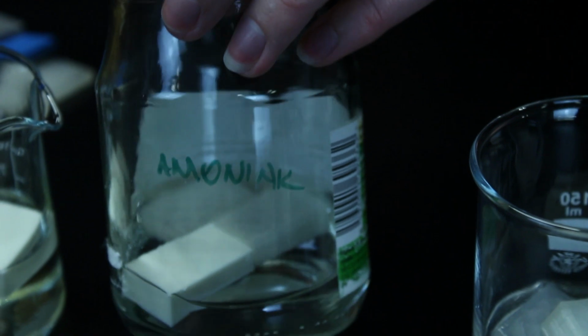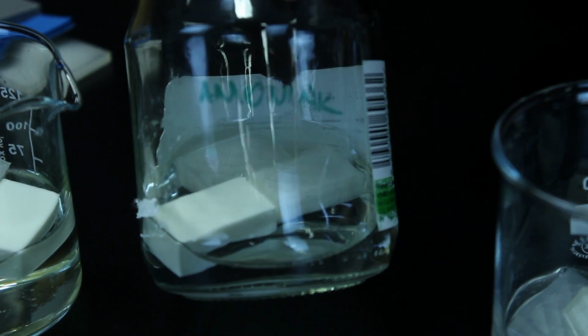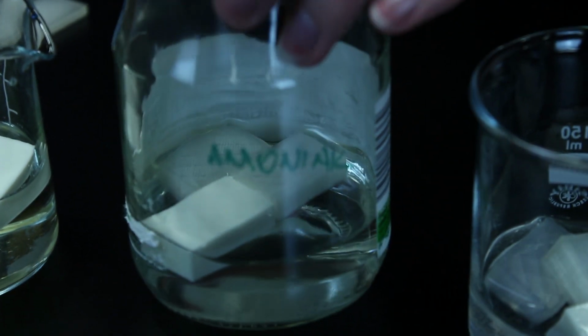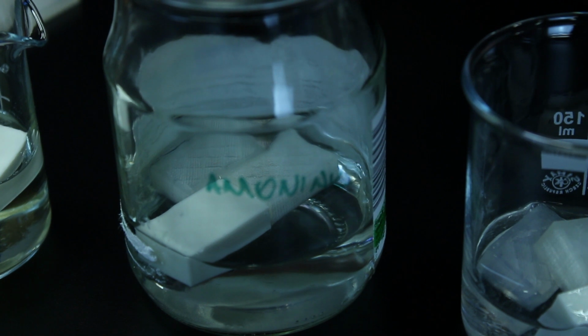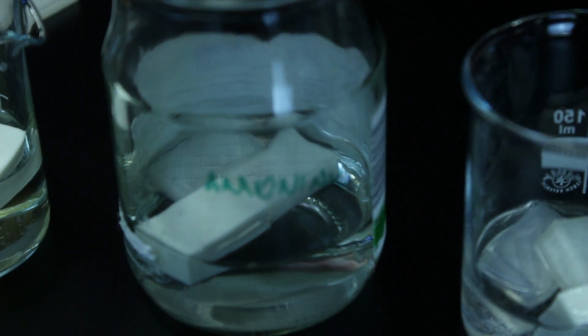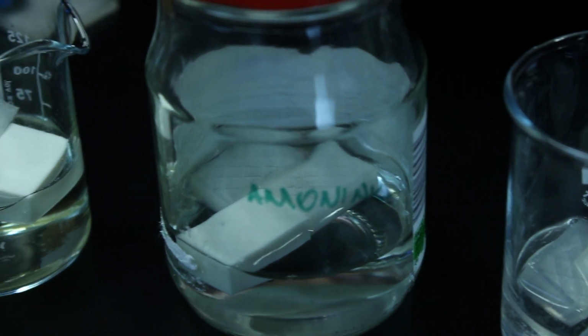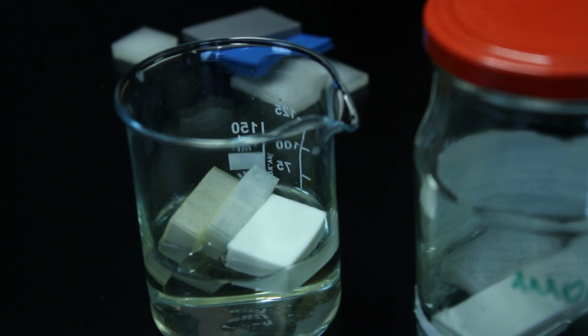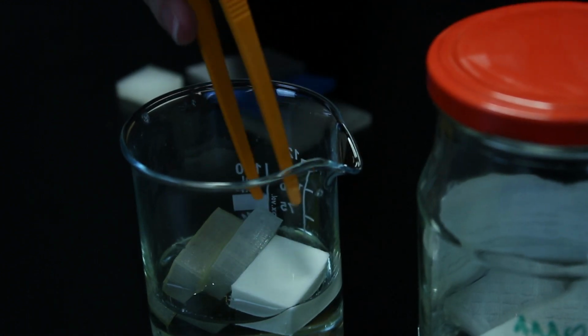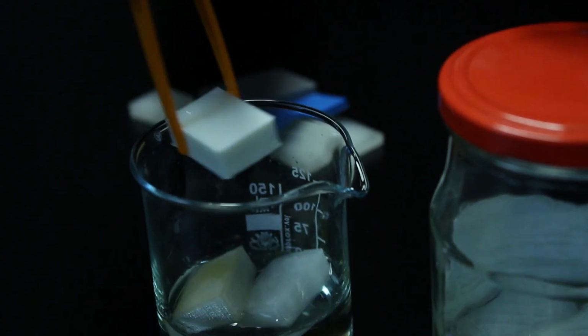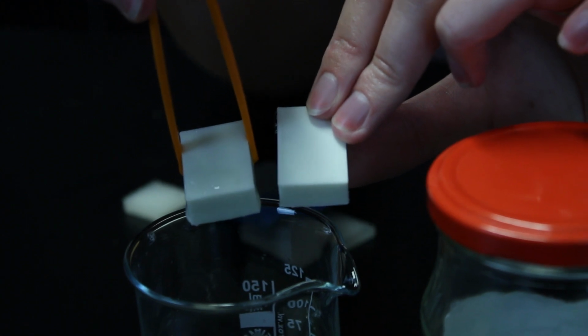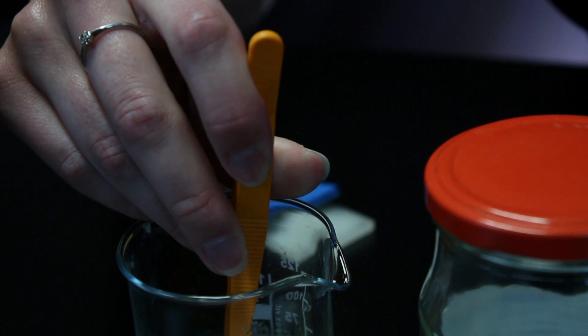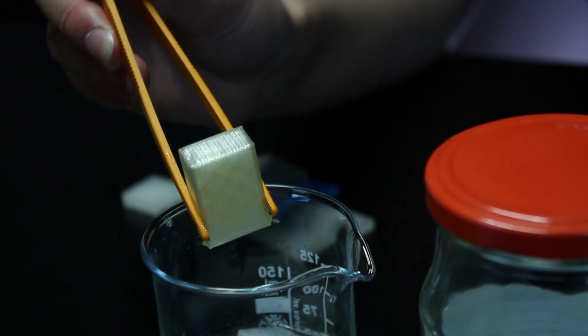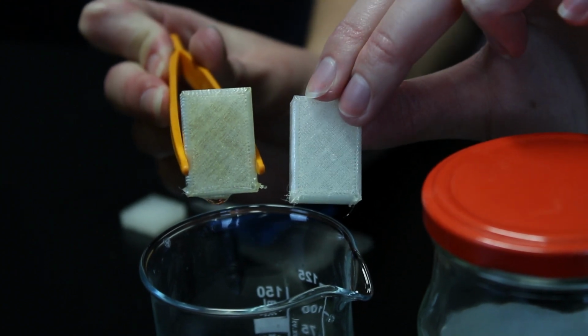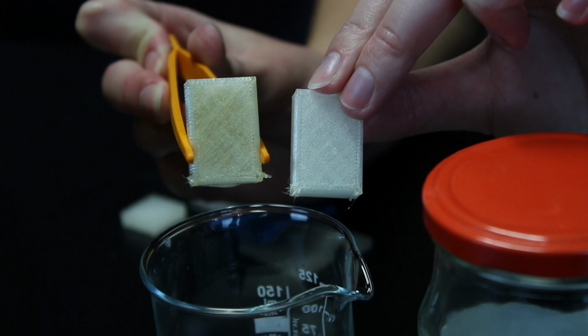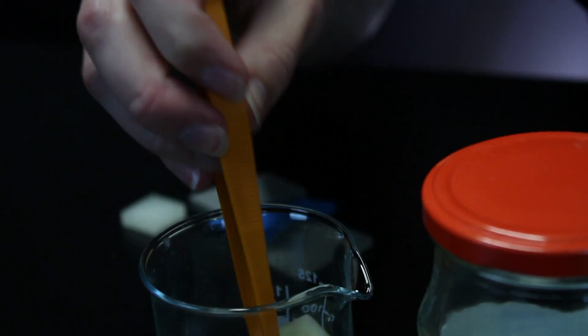In case of ammonia, I won't open it because we don't have enough ventilation in this room, but there was good resistance in case of all three flex fills, although TPU shows well. And the last one is sodium hypochlorite, also known as bleach. In case of TPE, there is a little bit of swelling. TPU should have good resistance, but it got yellow, and we can see that it got into the structure of the fill. And PBA